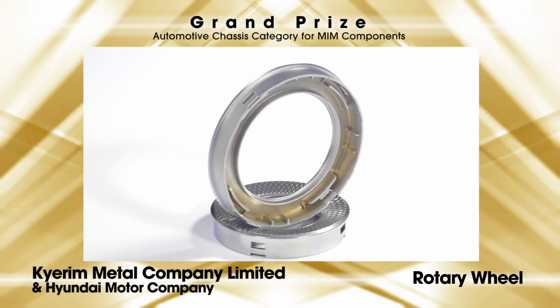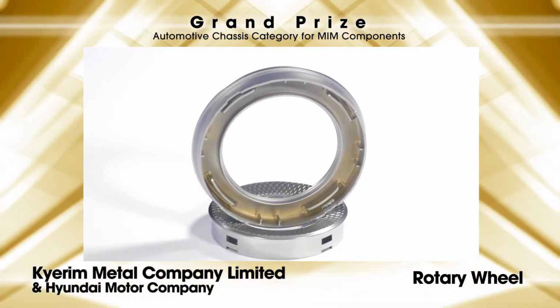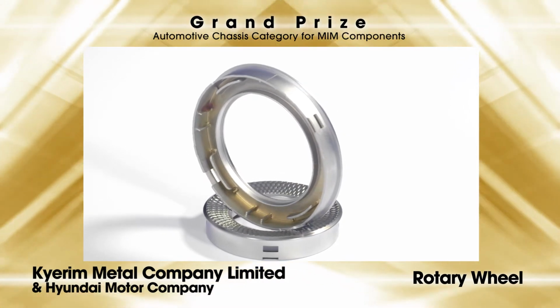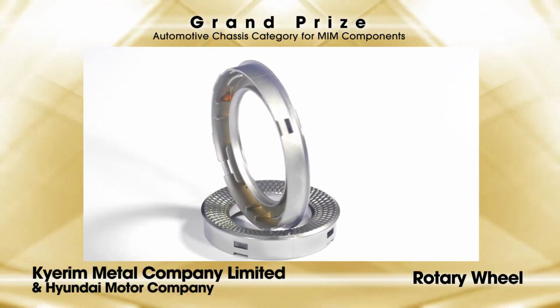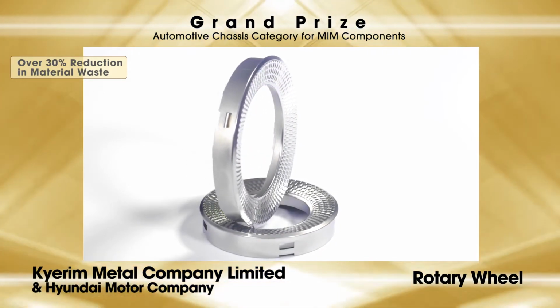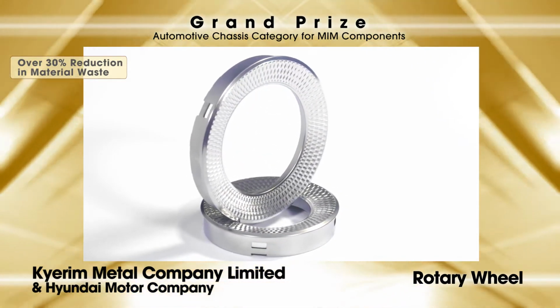The MIM components have 4 times the durability, and 0 discoloration or damage was observed, unlike in the prior electroplated plastic parts during service. Additionally, the MIM process reduced material waste by 30% because the previously electroplated plastic parts' gates and runners could not be recycled.